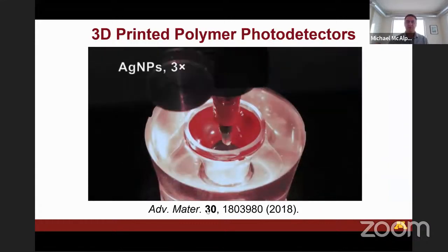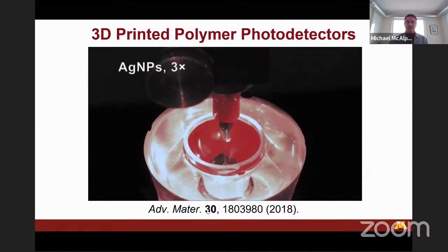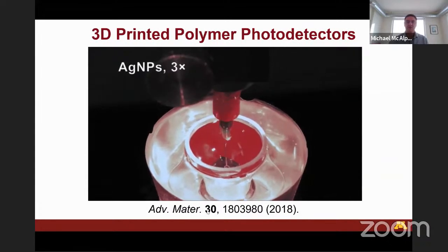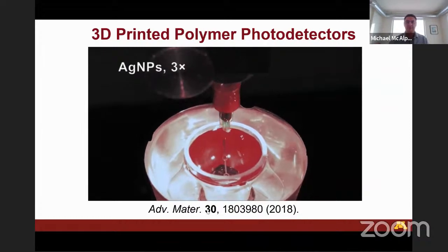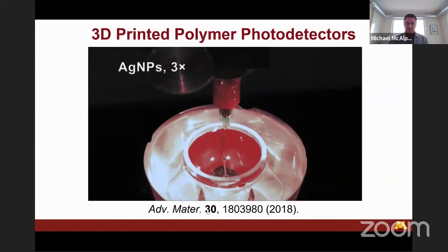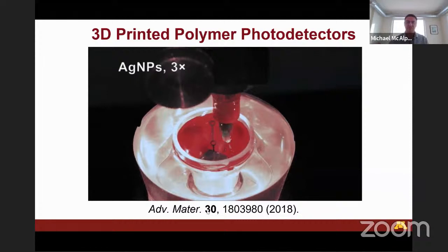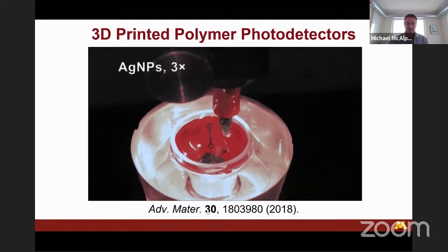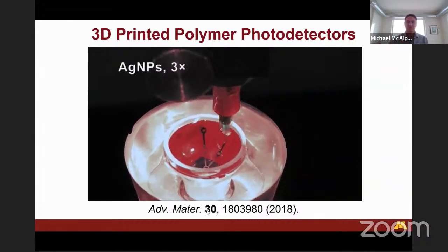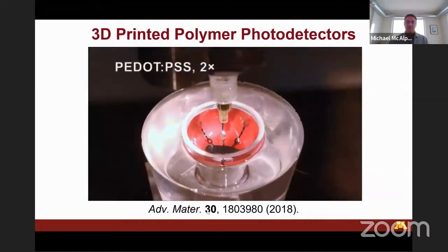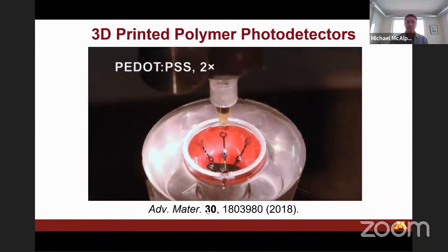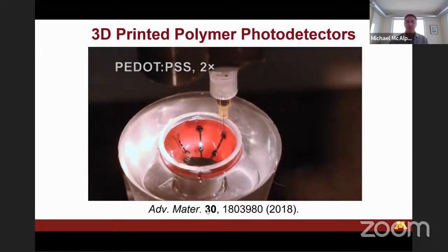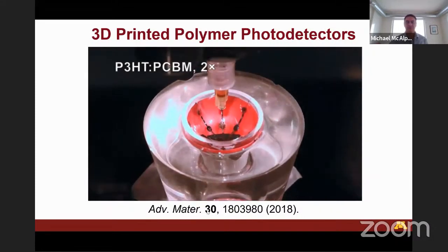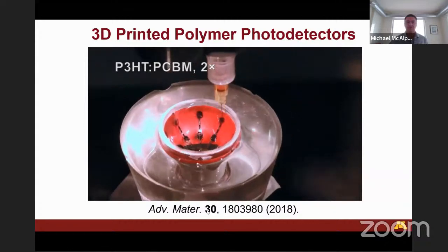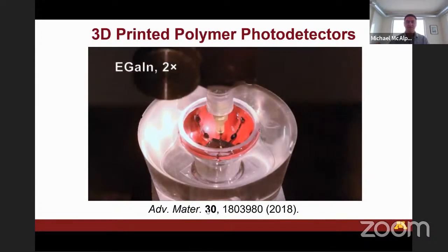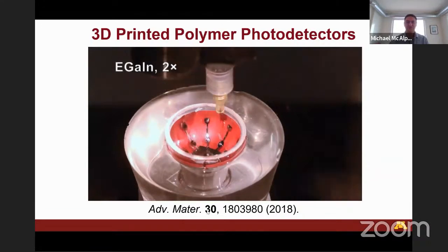And that's an older example, but a year or two ago, we also did not only LEDs but photodetectors, where we can print directly on the inner surface of a hemisphere. So these are entirely 3D printed semiconducting photodetector devices where we're printing the silver nanoparticles first as the bottom layer, up along the inner edge of this glass hemisphere. And then the next step after this, those rings there are so that we can actually visualize light through the device. And then we print this whole transport layer. And actually, Zigong's former student, Xuan Hizao, who also gave an EML webinar, has also published some interesting work on printing PEDOT:PSS. This is the semiconductor, a polymer blend semiconducting layer for the photodetector. And this is our top electrode, which is this blob of liquid metal. There's probably a better solution than this, but we haven't figured it out yet.